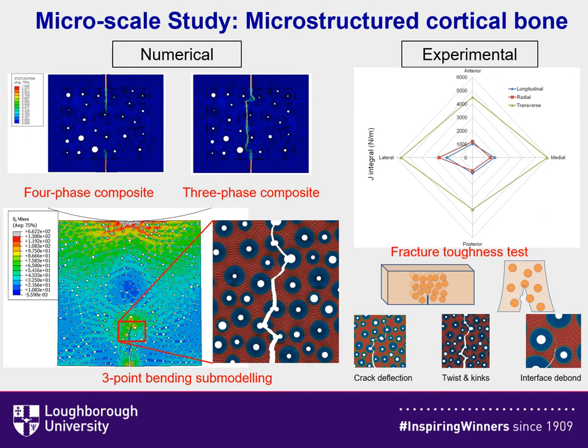This model allowed us to describe the main mechanisms of the fracture growth at the microscale level, including such mechanisms as crack deflection, twisting and kinking of the crack, as well as interfacial debonding. Speaking about the experimental part, we have also for the first time calculated the critical value of J integral for four different positions inside the same femoral bone.